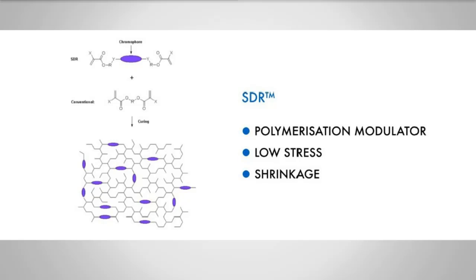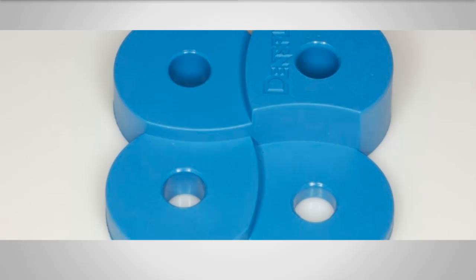The reason why SDR can be used like this is essentially that Dentsply managed to put something called a polymerization modulator into the backbone of the resin, which basically slows down the cross-linking of the resin material. So the material does still shrink. It's not a no-shrink composite, but as it's shrinking and setting, as it's curing, it develops low stress. So it's suitable for 4 millimeter deep layers. So double what we would normally be doing with a traditional composite.